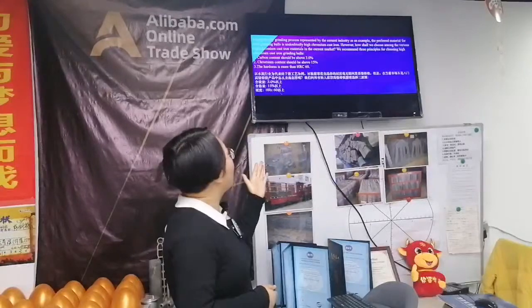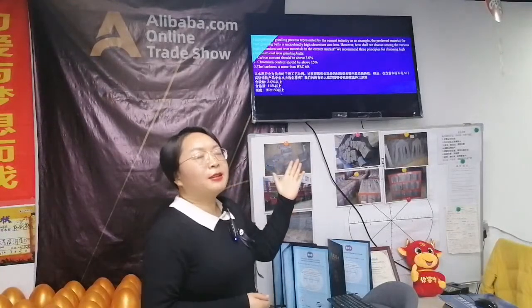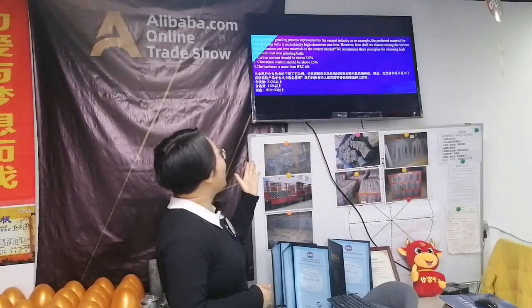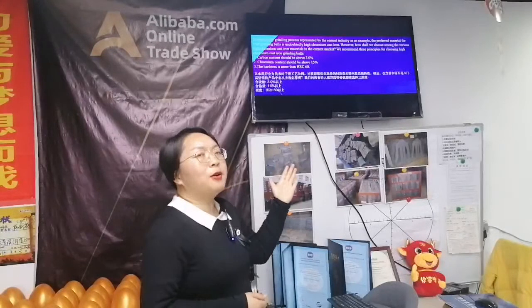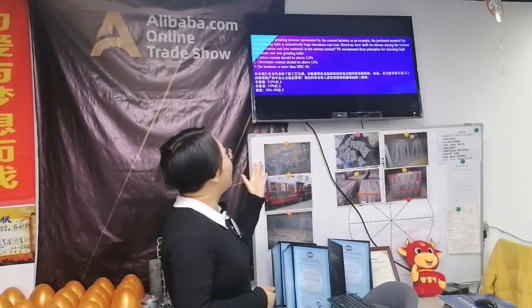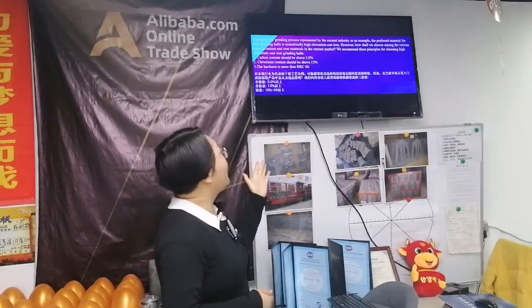However, how shall we choose among the various high chromium cast iron materials in the current market? We recommend 3 principles for choosing high chromium cast iron grinding balls. Firstly, carbon content of cast balls should be more than 3%. Secondly, chromium content should be above 15%. Thirdly, the hardness is more than HRC 60.